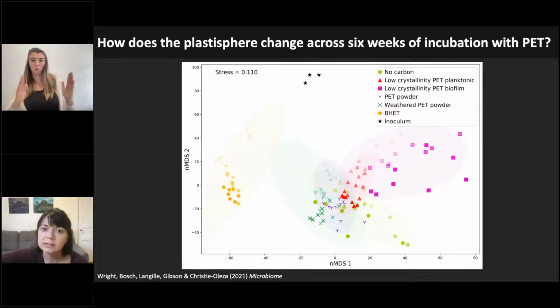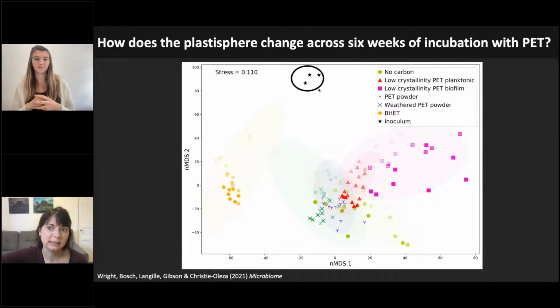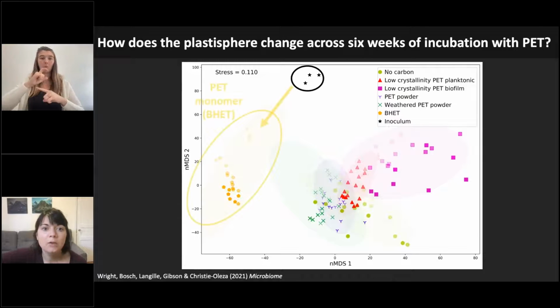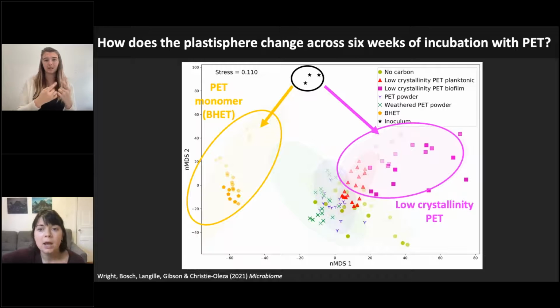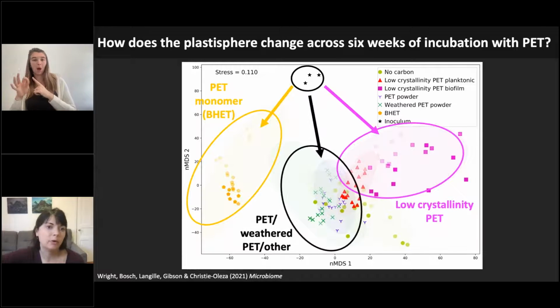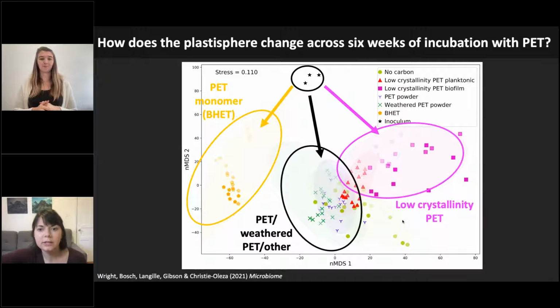So at the top here, this is our community that we took from the plastics collected from the beach. Over here, we have the microbial community growing with BHET, so the PET monomer or the breakdown product. Here we have the community growing with low crystallinity PET. And then here we have the communities that were growing with other types of PET. So this just shows us that our communities are different depending on the type of PET that they're grown with, and that they're all different from the starting community that we initially took from unidentified plastics. But what we were really interested in is which microbes are driving these differences.